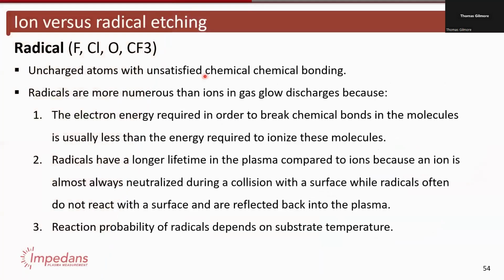This is short, it's just 2 slides. So radicals, they're uncharged atoms with unsatisfied chemical bonds. And these are more numerous than ions in gas glow discharges because the energy for excitation is typically smaller than what's required to ionize. And radicals also have a much longer lifetime in a plasma because the ion is pretty much always neutralized if it has a collision with a surface, but the radical can actually hit a surface and come back on. So you can have a high population of radicals that are long lasting.